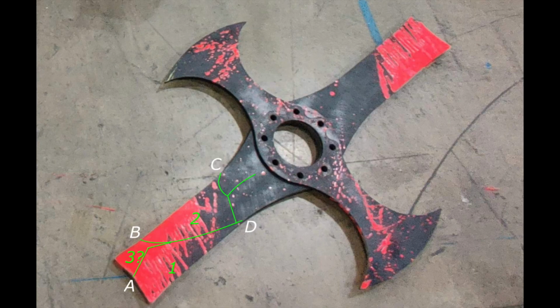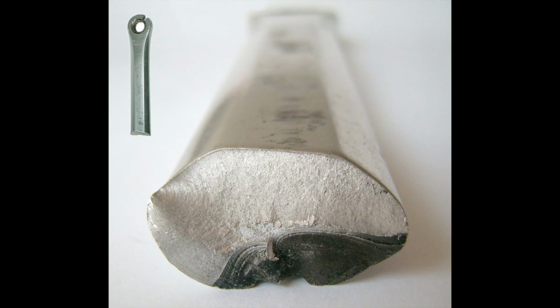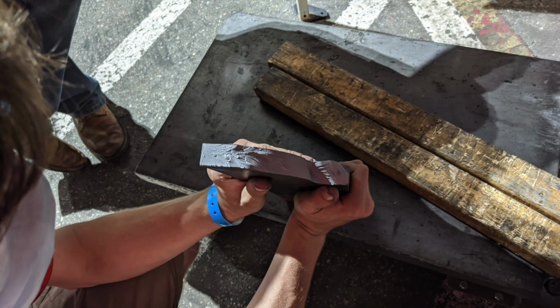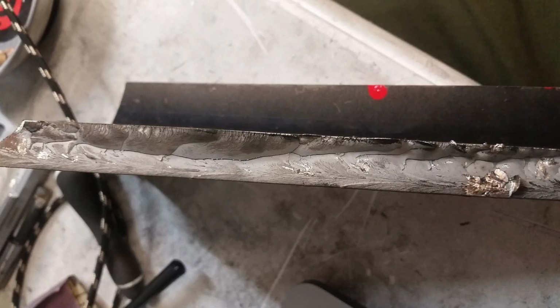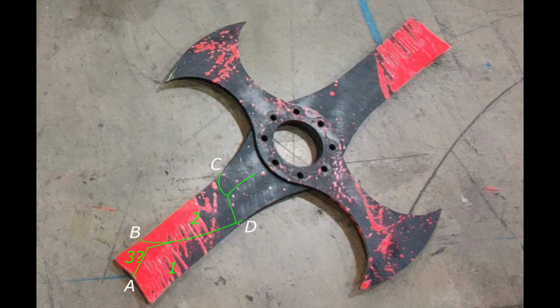One last possibility to consider is a tiny invisible fracture forming in the weapon, either during a previous match or during heat treatment. A look at the fractures themselves can help us tell whether this was the case, as microfractures sometimes leave discoloration on the fracture surface. The tri-bar doesn't have any of this, but the thick bar has a very irregular fracture pattern with some mild discoloration. It broke into several pieces, with the initial hit removing pieces 1 and 3, and a later hit removing piece 2.